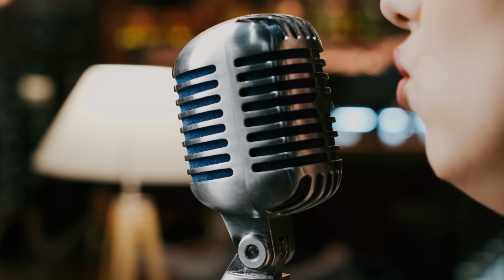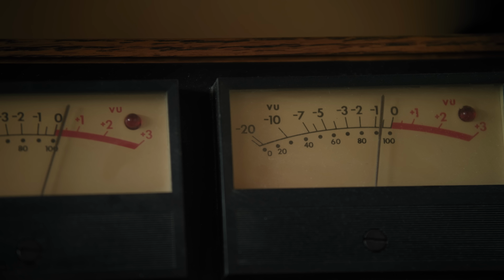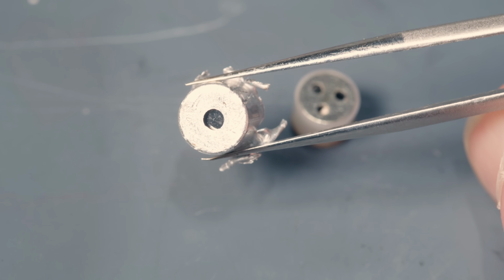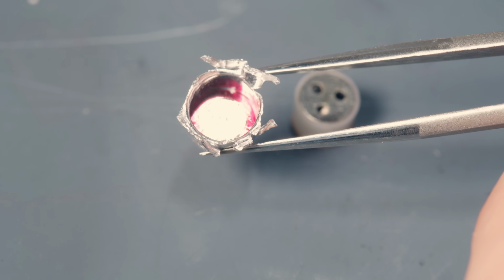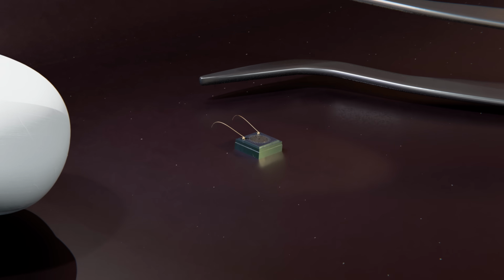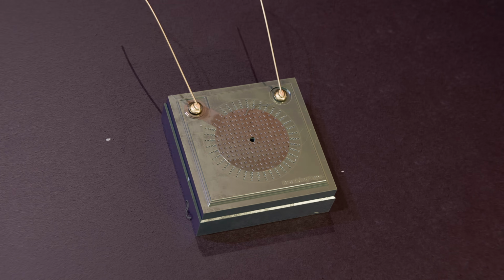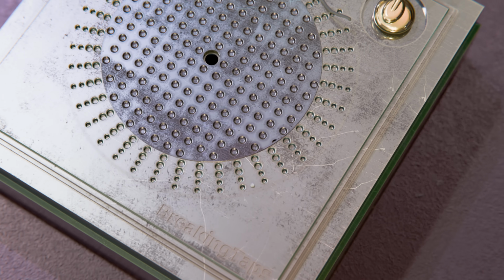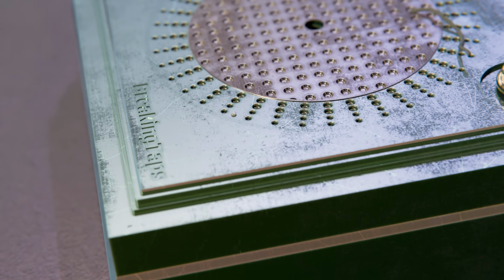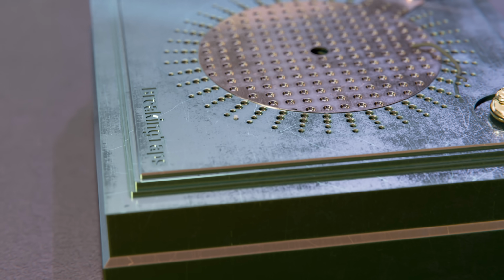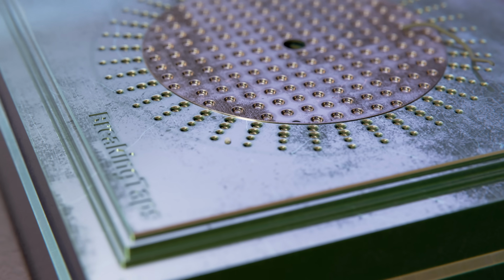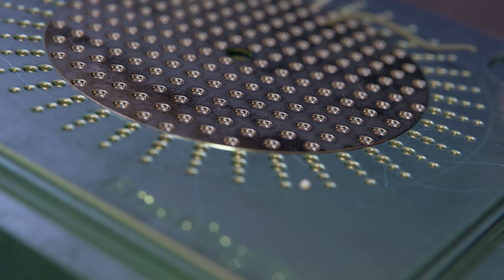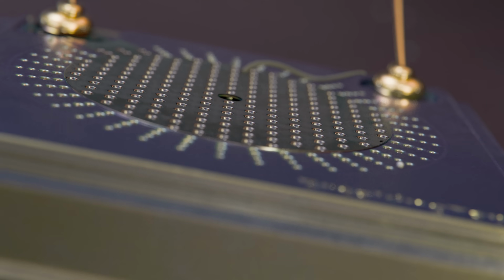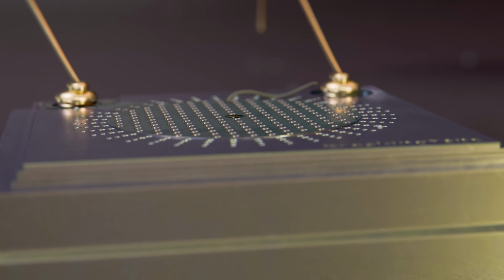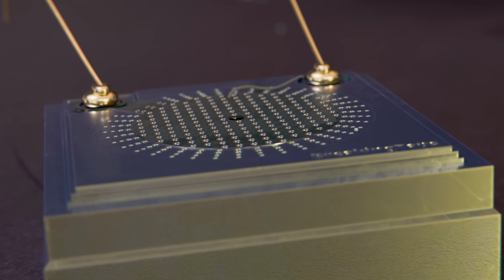Well, it's a microphone, which needs to turn sound and pressure waves into an electrical signal. Traditional microphones do this by using a thin membrane, which vibrates when sound waves pass by. But this MEMS microphone is too small to glue any kind of membrane onto. So instead, they fabricated the membrane directly out of the silicon. The top dimpled surface is that membrane. Sound waves hit the top surface and cause it to vibrate and deflect by very tiny amounts. Silicon is a hard, brittle, glassy-like material, but when it's thin enough, it'll deflect just like a plastic membrane.